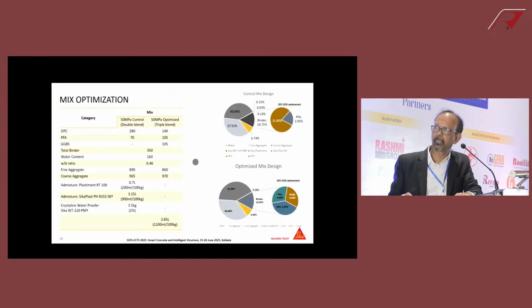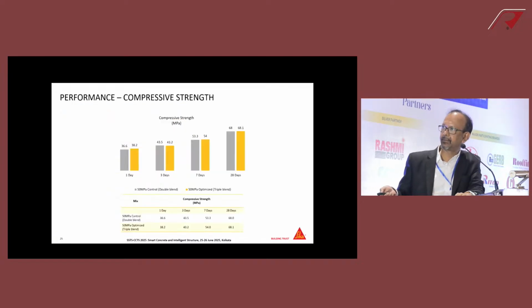So give you an idea about mix optimization. You see this 50 MPa double blend, which is basically with only cement and another supplementary material. But you convert this 350 into a triple blend, and I will show you the compressive strength does not change. Even early strength, slightly less, but it picks up, and that is the beauty. If you take 90 days, 180 days, it will be higher.